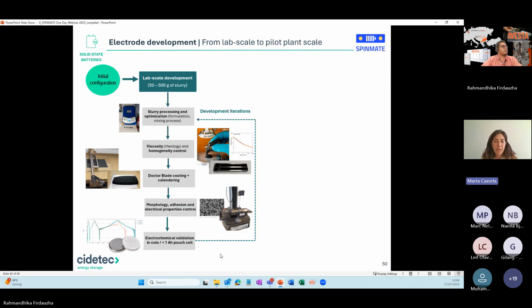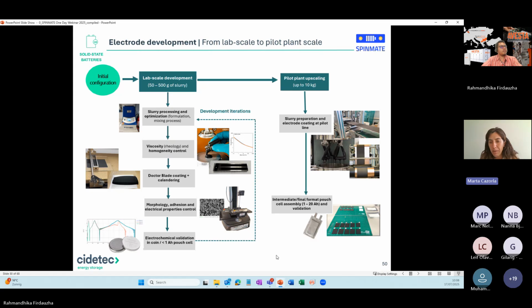Once this is done, this requires several iterations, and then once the formulation is optimized, we can go to a pilot plant upscaling, in which we prepare higher amounts of slurry, and for that we need higher capacity equipment, and this is the pilot line equipment that we will see in a minute. What are all these steps? They allow us to reach the final format pouch cell assembly that we need, and to again validate it, because then we also need to iterate back in the process until reaching the final configuration. So this is a bit how it's done.